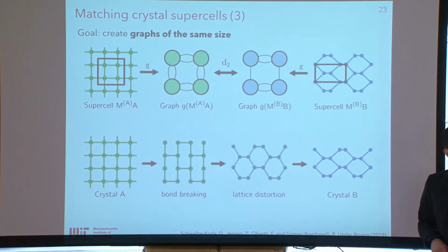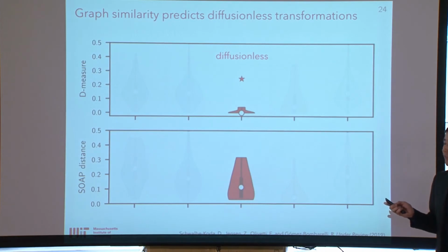Now, if we apply this reasoning to zeolites and compare it with all the results we found in the literature for such diffusionless transformations, we found that our graph metric explains all but one of the results in the literature of diffusionless interconversion. In contrast, some other descriptors which take into account, for example, common building units or framework density into a single metric of structural distance, are not as predictive as the graph similarity.